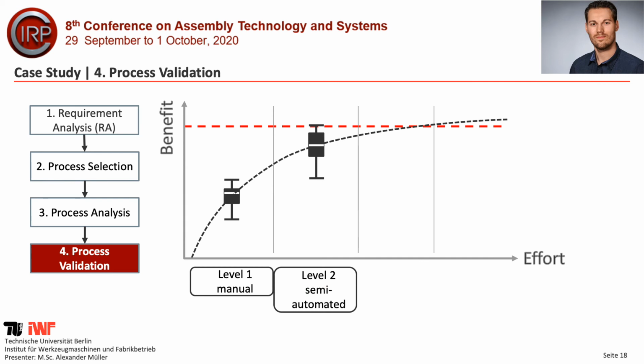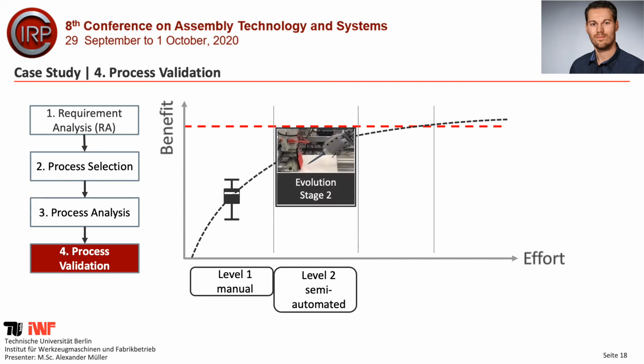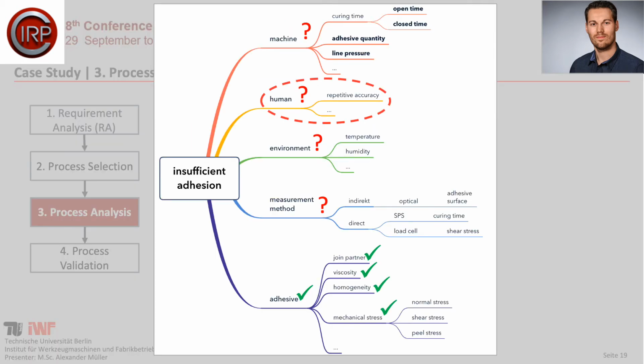So we went to level 2, the semi-automated test bench, where we replaced our human interactions with automated axes. Then we could take the human out of the equation, and we added some measurement methods so we can directly measure our curing time and our shear stress, and we can also vary the parameters of our machine. So we can change our parameter settings, so we can control the curing time and the line pressure, but we still have a question mark on the adhesive quantity.